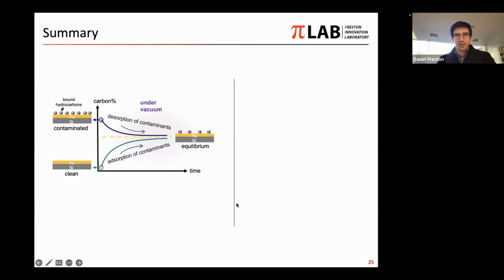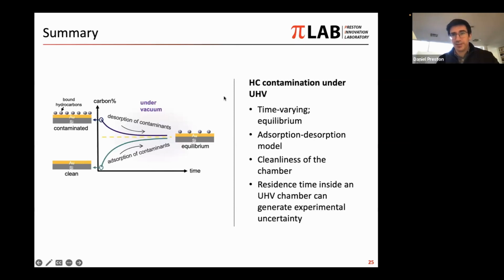So basically, we looked at this ultra-high vacuum storage. We found that we, in this case, have this time-varying behavior. They both approach an equilibrium value inside the chamber that's likely related to the chamber walls themselves having some contaminants. We use the adsorption-desorption competition model to describe the behavior over time, and said that maybe the cleanliness of your chamber is quite important, right? So maybe in this case, the XPS chambers are heavily used equipment. We have lots of samples going in and out. And maybe the walls of the chambers themselves are quite dirty. So this is something that you should really consider when you're trying to run experiments and carefully calculate surface characteristics, because even over the time scale of hours, this can alter your results.